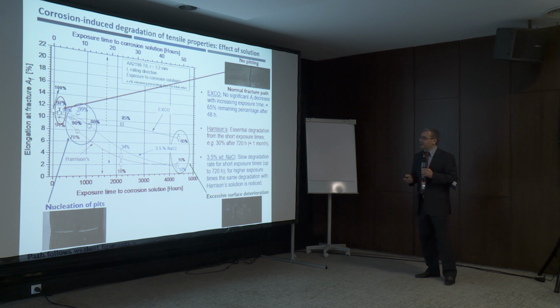And finally, for the sodium chloride, it's something different from the Harrison one, showing that the nucleation of pits is rather prolonged, and nevertheless the degree of degradation is similar to the Harrison one. So this means that the corrosion degradation rate, as far as elongation at fracture is concerned, is more or less the same. And this is something that we will try to investigate in the near future.